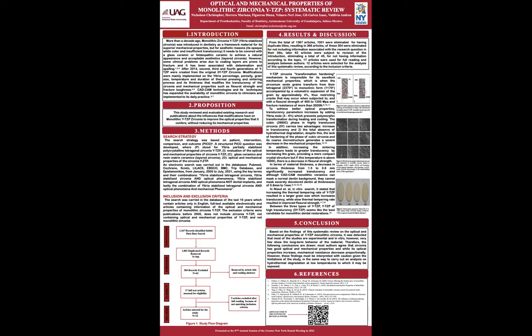And for the rest of the discussion, we talk about the different modifications implemented on zirconia. For example, Y-TZP. When we add more yttria, an oxide stabilizer, it can prevent that polymorphic transformation that we talked about and let zirconia stay in its cubic phase. Cubic crystals are larger than tetragonal crystals, so when light is transmitted through the restoration, it goes through fewer boundaries and fewer porosities, and for that reason it appears more translucent.